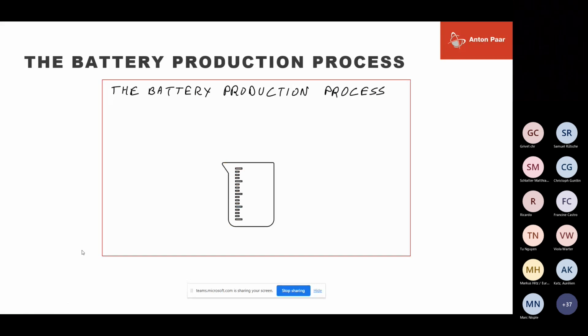This animation is a simplification of the process of battery cell production, which is a complex procedure that follows a process chain of a large number of consecutive individual steps. In the classic example of a lithium-ion battery, a typical cell manufacturing process starts with the production of the electrodes. For this purpose, the powder raw material of the electrode, for example, NMC for the cathode and graphite for the anode, is mixed with a binder, typically PVDF, as well as some conductive additives. Then a small amount of solvent is added, such as NMP, which is an organic solvent. Everything is then mixed well together to form a very homogeneous slurry.